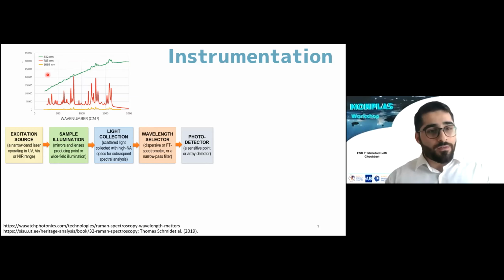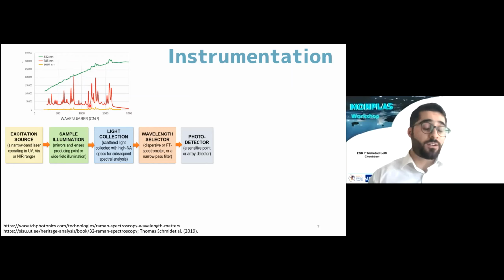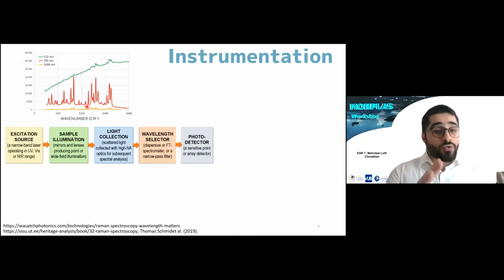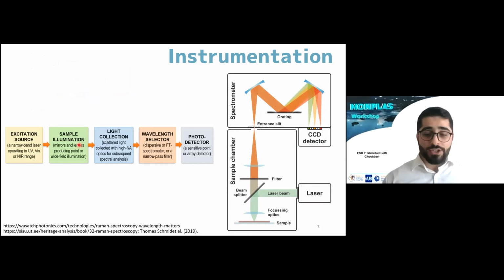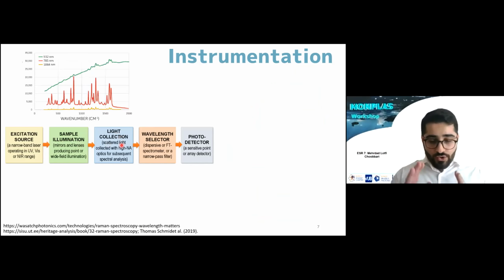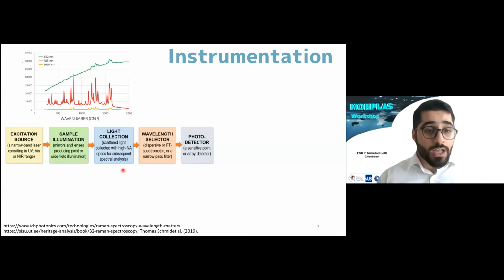By going even to longer wavelengths, for example, 1064 nanometer, you see that the background is almost 0, while the intensity is also decreasing. So you can see how it is important to consider your sample, to consider the situation of your experiment, and to choose the proper wavelength. The same is true for other parts. For example, the sample illumination and the light collection should be quite carefully designed to help us to efficiently illuminate our sample and also collect the Raman signal. As I mentioned, the Raman signal is very weak, so here we need really nice collection optics to help us to measure the Raman signal very effectively.